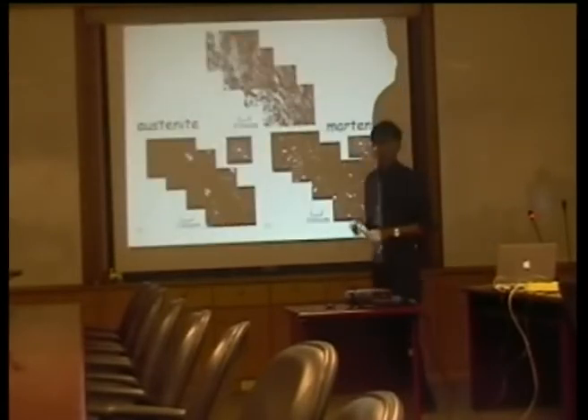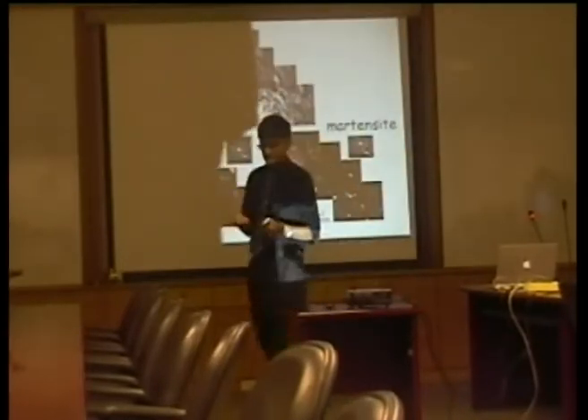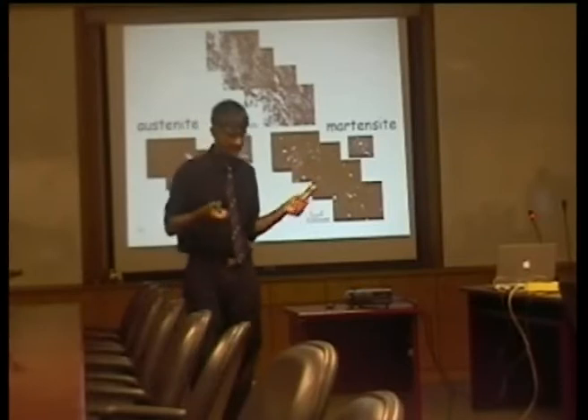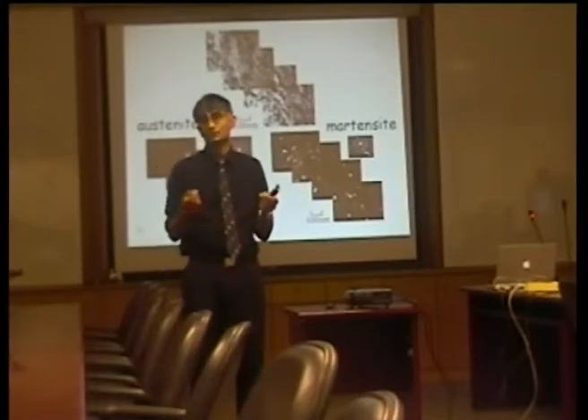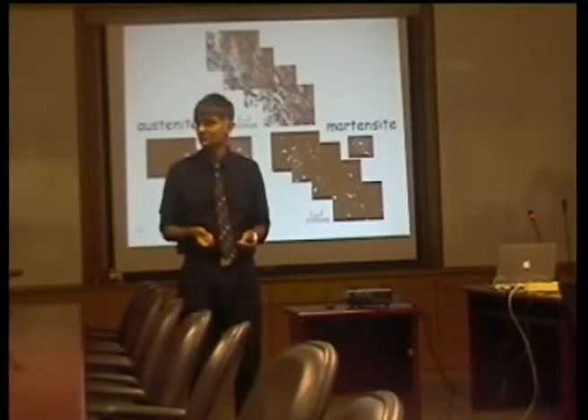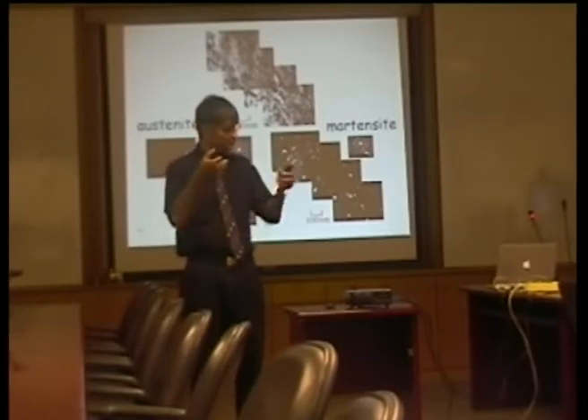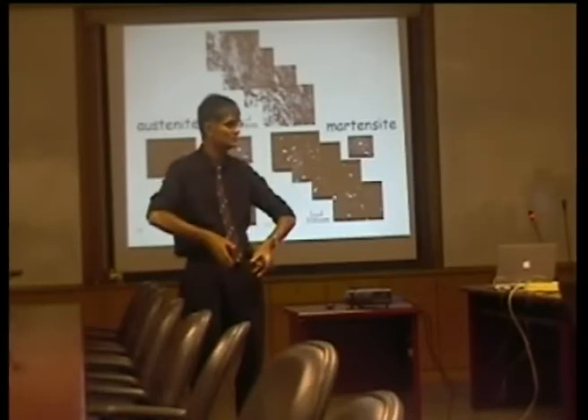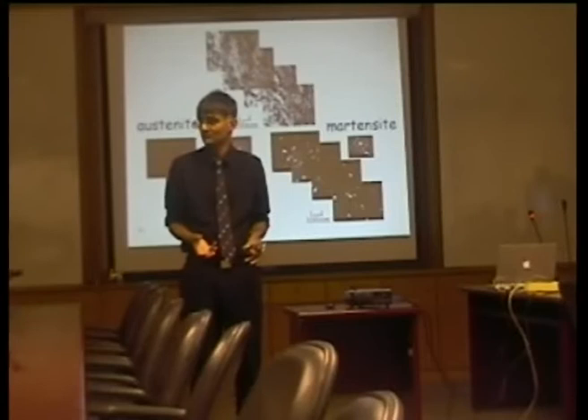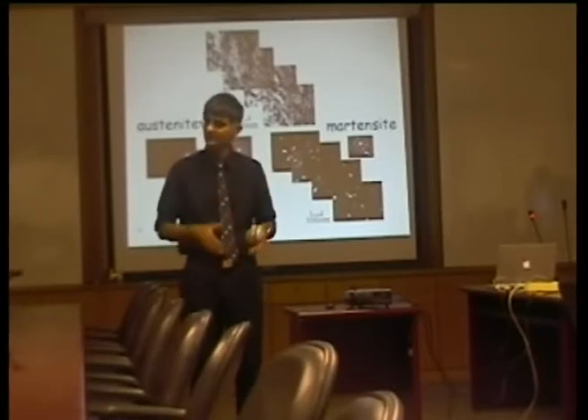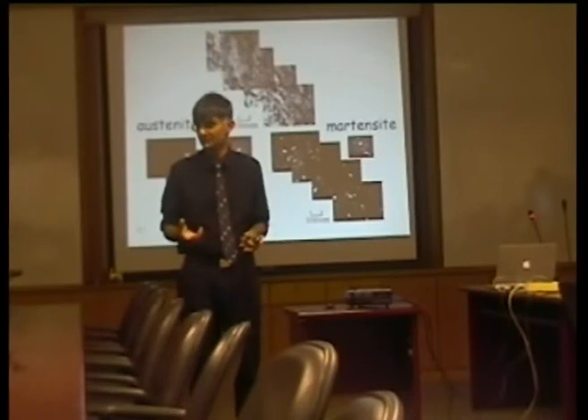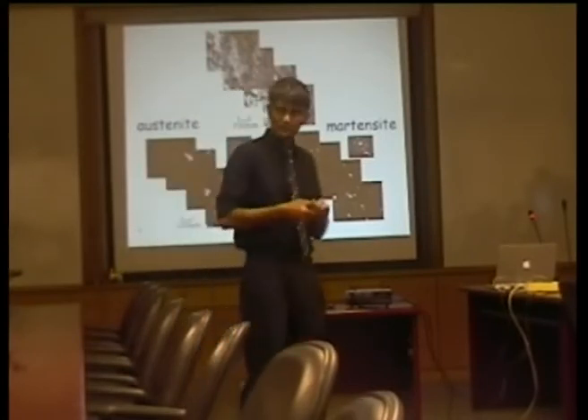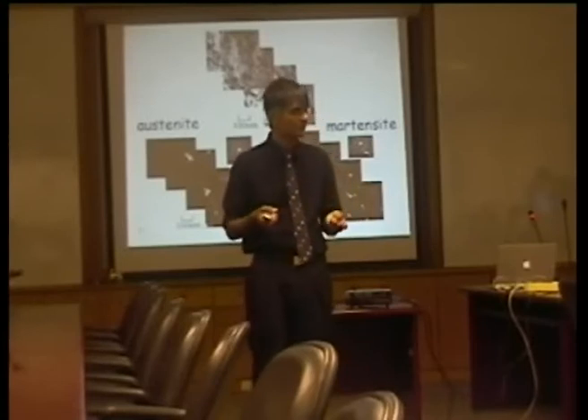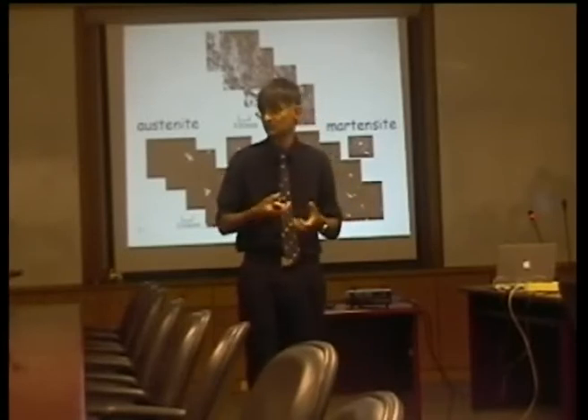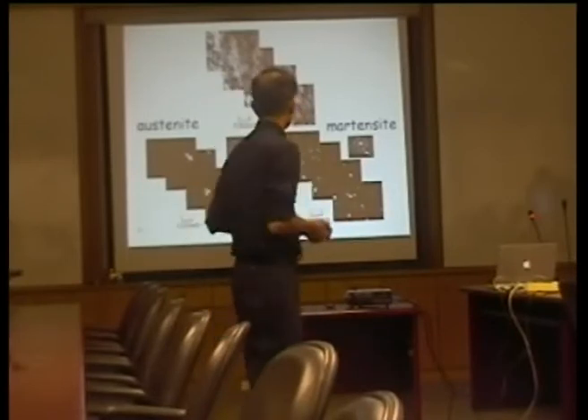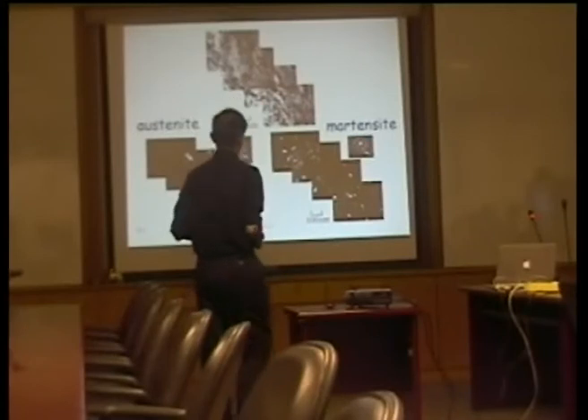Now, of course, austenitic stainless steel, I will show you, and of course it is well known, that austenite is not the stable phase at room temperature. It is a metastable phase. All these austenitic stainless steels are not really stable austenite. They want to transform to ferrite, but by cooling rapidly, we retain all the austenite and we get a fully austenitic steel. So if you deform it, then you give a chance for the austenite to transform. Okay? The stress and the strain helps the austenite to undergo phase transformation. And the transformation that happens is it goes to martensite.